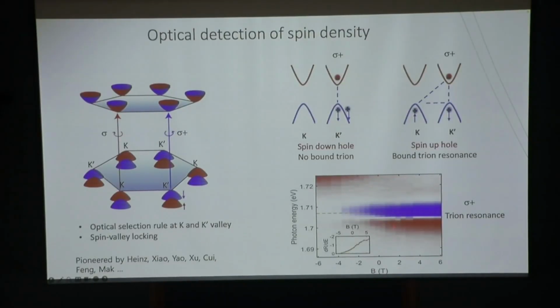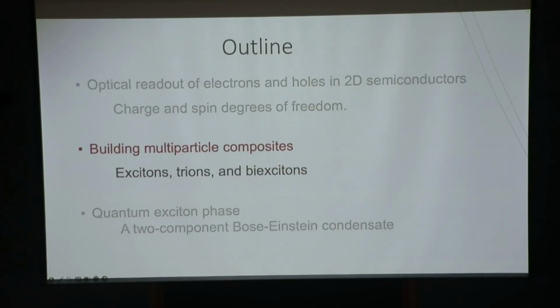At zero magnetic field, let's say we dope the system, half of the holes are spin up and half of the holes are spin down. When you apply a positive magnetic field, more spins will be up, and then the trion signal intensity increases. When you apply a negative magnetic field, the spin up holes are depleted, and you see a reduced signal. So basically with this optical circular polarization, we can read out the spin density directly for both electrons and holes. Okay, so that is the background. Those are the tools that we are going to use to probe what's going on in the electron-hole system.